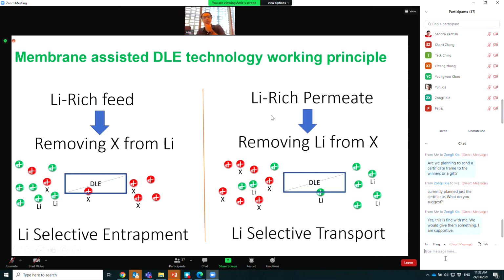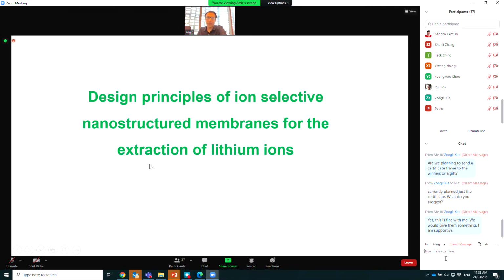Similar to any DLE process, membrane-assisted DLE technology can be categorized into two different types: lithium-rich feed and lithium-rich permeate. In lithium-rich feed, basically the target is to remove impurities from the feed, and you will end up with lithium-rich feed. Whereas for lithium-rich permeate, the target is to transfer lithium to the permeate side, and then you will end up with lithium-rich permeate.